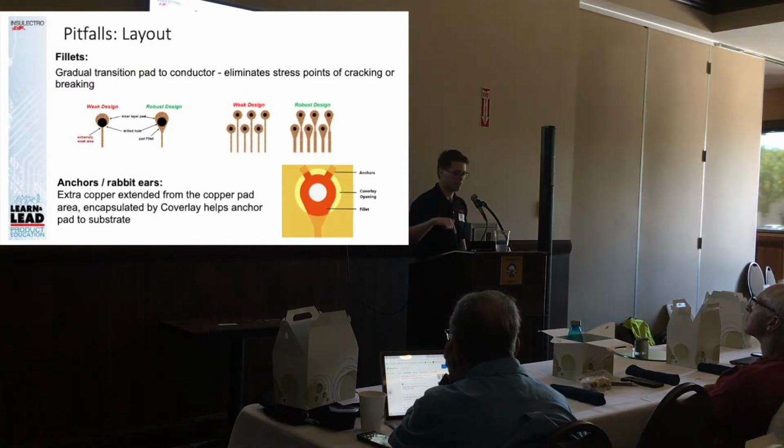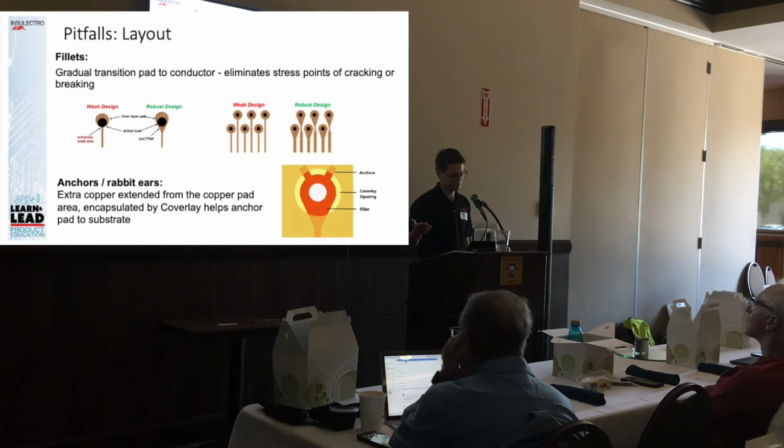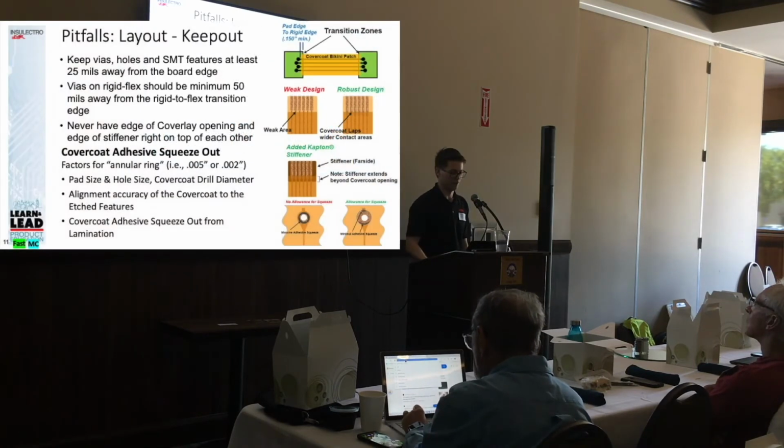On the bottom there is something called rabbit ears. I don't see it a lot, but it's there from time to time. It's kind of an artifact of days bygone, but people will essentially increase the surface area of the pad, so when you're going through any kind of heavy bend or load, you're not going to have a delamination event from the copper to the base material. All-polyimide flexible materials that are 4204/11 generally don't have these issues, so you don't need ears, but again, it's an artifact.